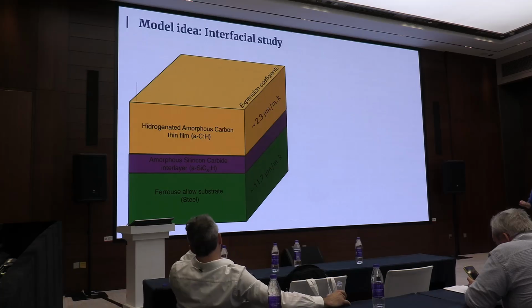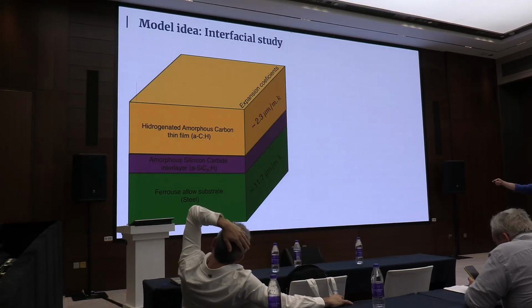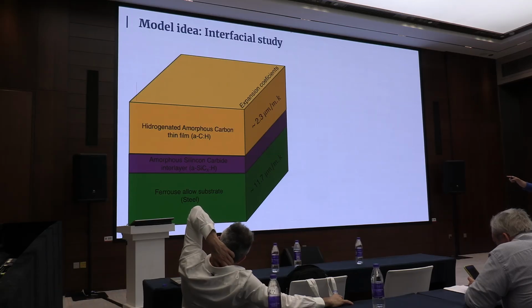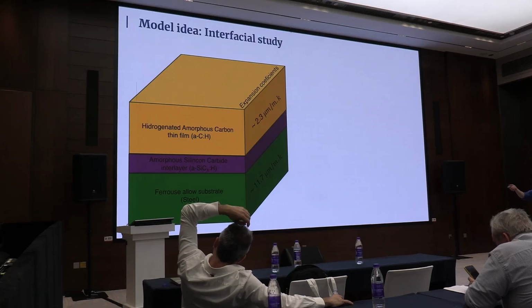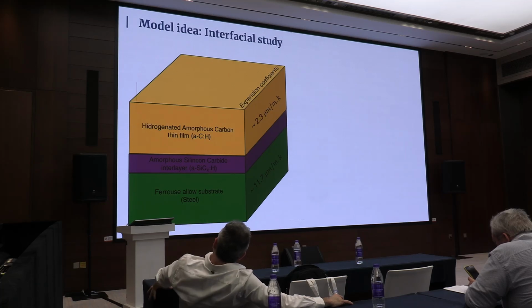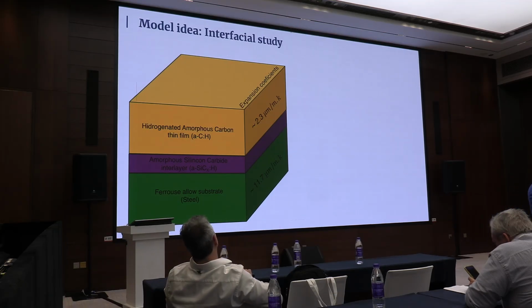So to solve this, the idea is adding a third interlayer in the middle. This interlayer has an expansion coefficient in between those, but it has more because the carbon is good to be added to another carbon for the upper layer, but the silicon is good for being added to the iron. So this is a good candidate to be an interlayer to make a bridge between both big different expansion coefficients that we have.